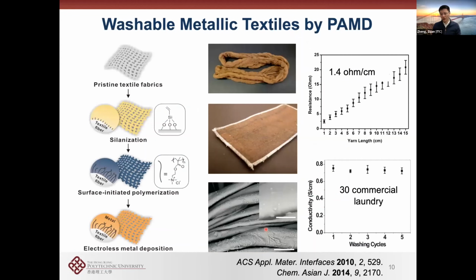So we changed this chemistry to apply it onto some soft substrates, for example, textiles, fibers, yarns, and fabrics. So you can do all this nice coating of metals, right? So we started to grow the polymer, and after we grew the polymer, in this case, we deposited copper, which is typically very difficult to deposit.